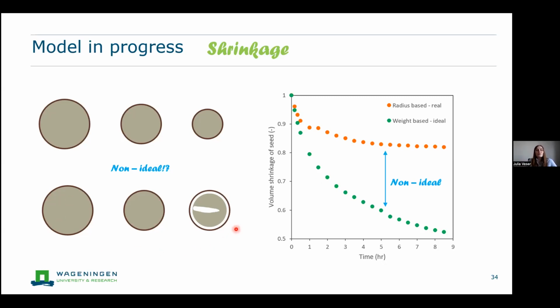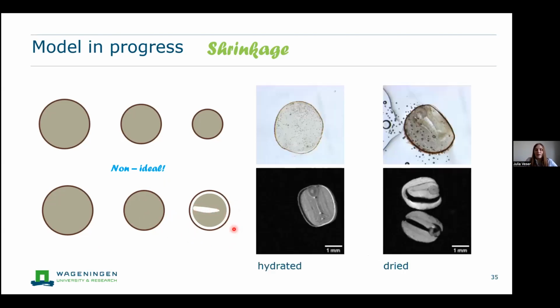And actually, we could also see this non-ideal shrinkage in our MRI images. And here depicted graphically, at a certain moment, probably the overall radius doesn't shrink anymore or less. And inside, we have a development of air pores. And here, again, our MRI images where we clearly saw this phenomenon happening. Also on top, you see some microscopy images where we make thin slices of the seeds. First, we have the hydrated one and then the dried ones, where we really also see these air pockets evolving.